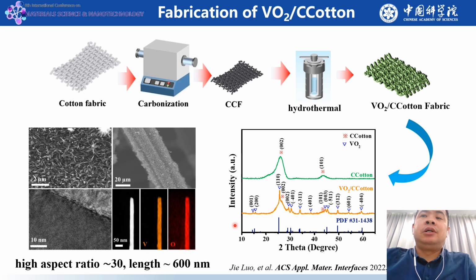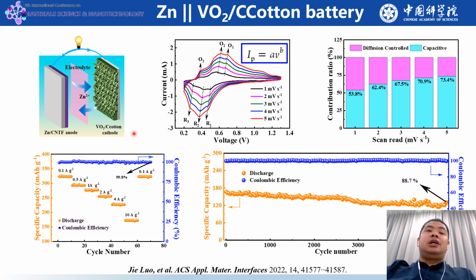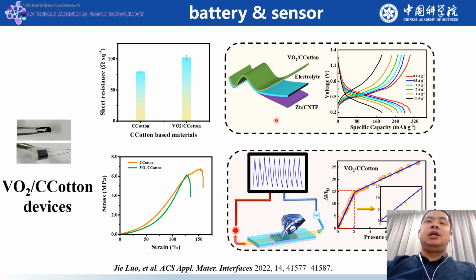And the vanadium dioxide presents a rod structure with a high aspect ratio of 30 and a length of 600 nanometers. After sandwich structure assembly with vanadium dioxide cotton cathode, gel electrolyte, and zinc anode, a 2D zinc-ion battery was obtained. It presents a distinct capacitive property and good rate capability, as well as a long cycle life over 5,000 cycles with 88.7% residual capacity.